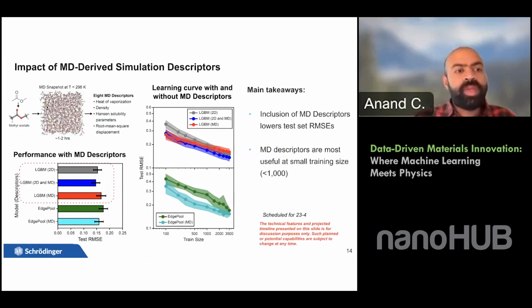So the MD descriptors that we generated were things like heat of vaporization, density, and the Hansen solubility parameters from MD, and the root mean square displacement. So we had a total of around 8 MD descriptors that we calculated from these amorphous systems of these molecules. And we plugged in these descriptors to the tree-based models and the graph-based models.